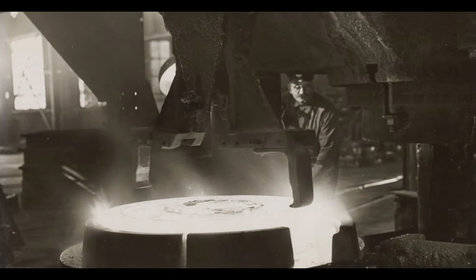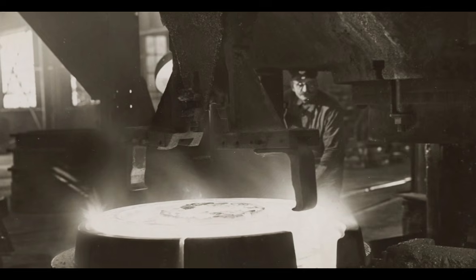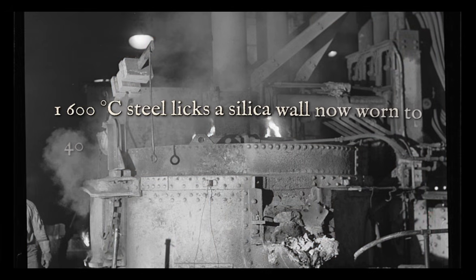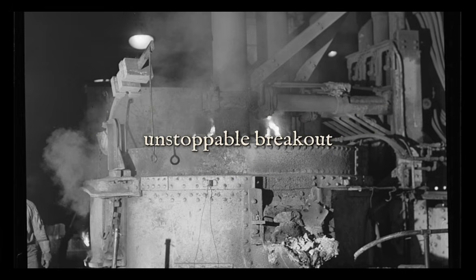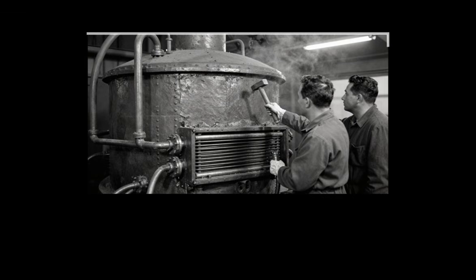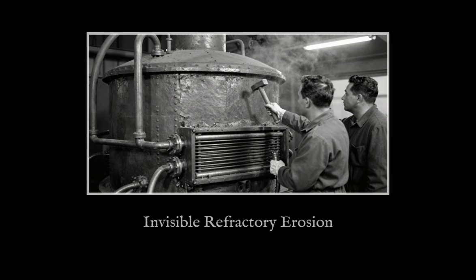Slag, the layer of impurities and oxides that floated on the surface of the melt, attacked the refractory chemically, dissolving the silica matrix at the lining's upper boundary. Mechanical abrasion from the charge material being loaded and shifted added to both processes. The lining that passed visual inspection after one heat might be at the edge of containment failure by the third heat of a shift, with no external indication of how thin the remaining section had become.